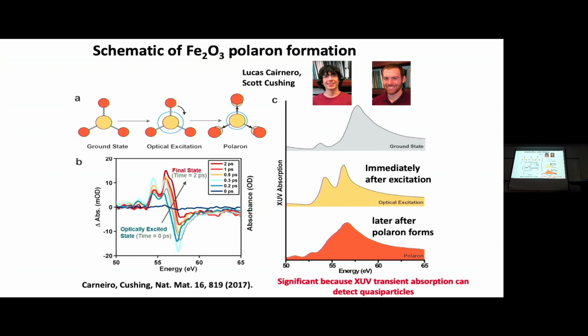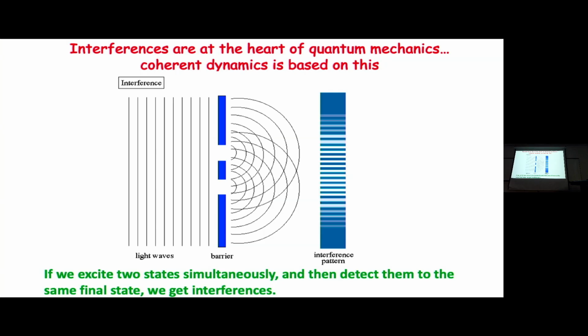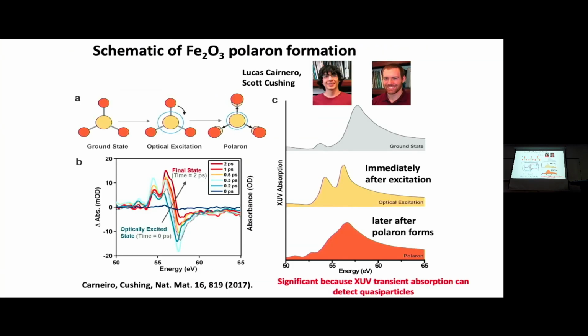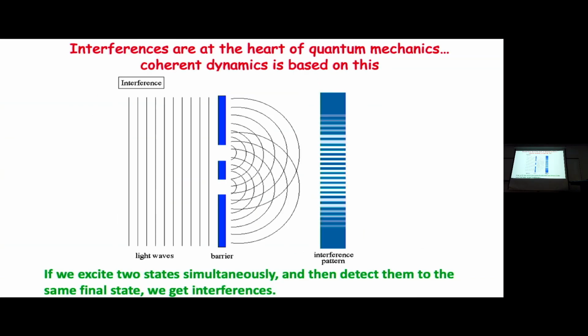Not always. You know, we hunt all the time in our lab for any signatures of quasi-particles, but this is one that's very evident, that we see the formation of this polaron where the electron charge around the iron is strongly influenced by the vibration, basically, by the change in structure due to the vibration. And this polaron lifetime is 2 picosecond? Yeah, that's very long. In this material, it turns out that the charge transfer and the polaron is long-lived. Not always in every case.